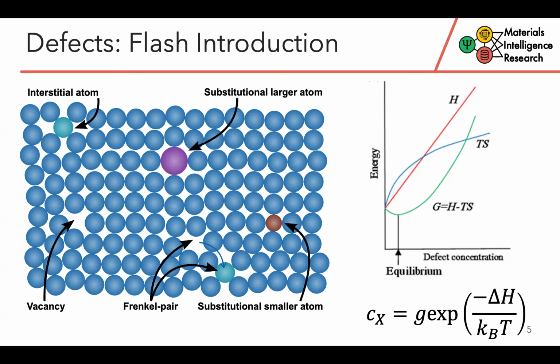And just thinking about why we have this configurational entropy contribution. Well, if we think about having a fully ordered, perfect crystalline material, and we add just one defect to that material, there are many different possible sites at which we could place that defect, which would all be symmetry equivalent. And so the fact that we have this extremely large multiplicity gives us this strong configurational entropy contribution.